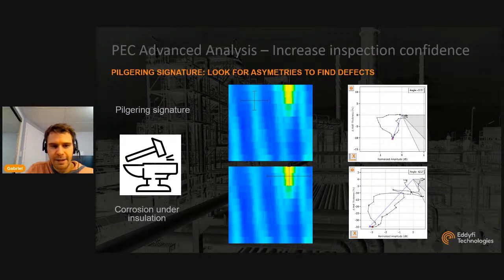Pilger signature, that helix pattern that you see here on the pipe, is not so common in the field, especially in refineries, because the pipes are thermally and mechanically cycled over time, and that does kind of a healing process on the pipes, and that takes off the cold work marks or localized change in magnetic properties that were induced during the manufacturing process of the pipe that can affect the PEC signal. So you see that more often on pipes that are not very hot or not under high pressure or quite new, especially in manufactured samples. So the tool is not able to differentiate that from a defect.